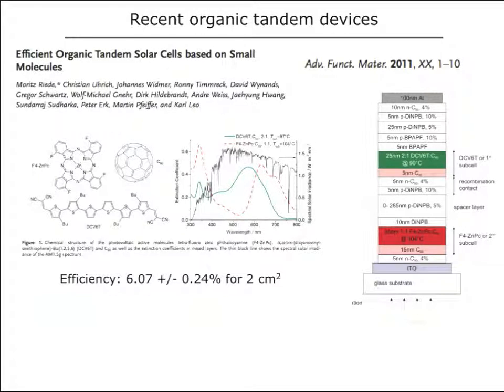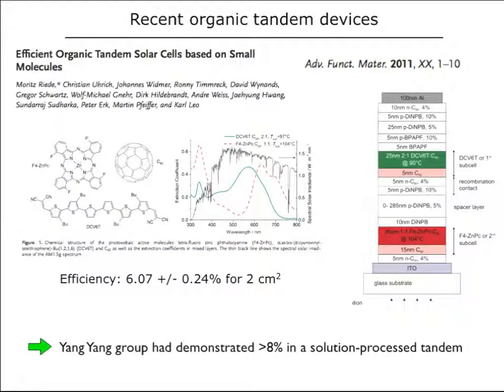There's been even more results out of the small molecule group, the group at Dresden, where they're using combinations of fullerenes and in this case oligothiophenes, and they've gotten over 6% device in a recent publication on a multi-junction device. One very exciting announcement. So Yang group has certified well over 8% in a solution process tandem. So no vacuum deposition except for the electrodes. So a tandem device well over 8% has been demonstrated. So I refer you to Yang for a little more details on that.